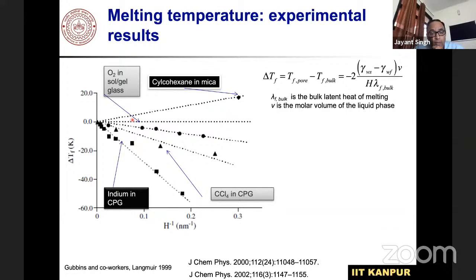Experiments have been done around 2000, 2002. This is oxygen, this is indium in CPG, a glass. Many people saw that this is a linear behavior. Of course, finding the freezing temperature in pores is itself an art in experiment, so you could see not many data points are there. But people were very happy that if they evaluate delta TF as a function of 1 by H, where H stands for the pore size of the material, they observe linear nature.